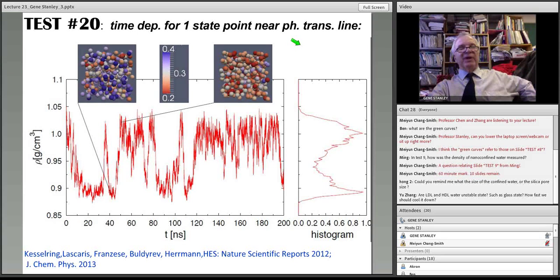You see the density flips from the high density phase, you remember was 1.05, to the low density phase, you remember was about 0.9. And then it flips back to the high density phase and back to the low density, and high density back, all the way down, up, down, up, down, up, down, very chaotically. Then it just goes into complete chaos. If we shine a flashlight from the left to the right, we see this projection here with one big peak at around the high density value and one second peak at the low density value. And so this is what time dependence shows you.